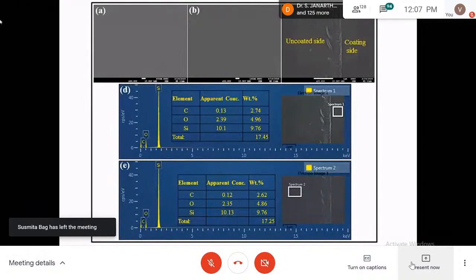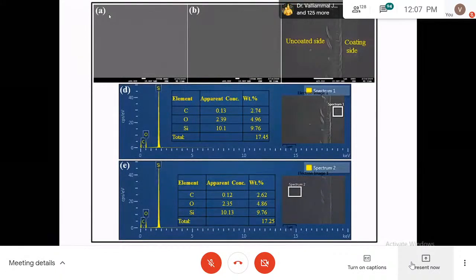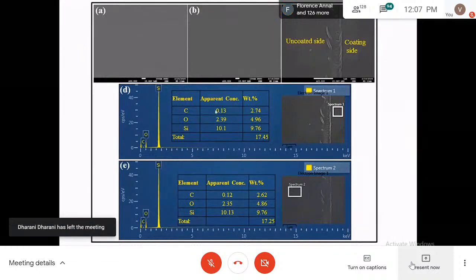A is representing the 7.5 minutes cyclohexane coated sample, and B is the 10 minutes cyclohexane coated sample, and then C is showing the uncoated side and coating side. We have to match some area. What happens on this coating side? We can clearly see the higher concentration of carbon.